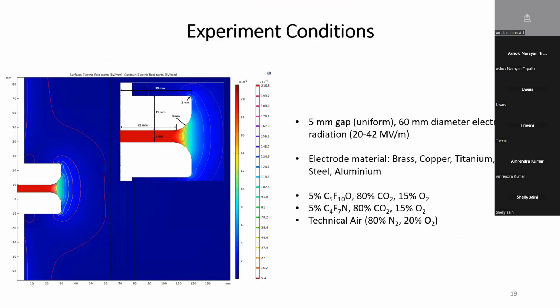Coming to the experimental conditions, I chose a single gap distance of 5 millimeters, uniform, with a 60 millimeter diameter electrode. We didn't use any external UV radiation, because UV would be the source of your starting electrons. Instead, we did a very slow ramp. And accordingly, with the geometry that we have, we ended up with 20 to 42 megavolt per meter, which was exactly what we wanted.